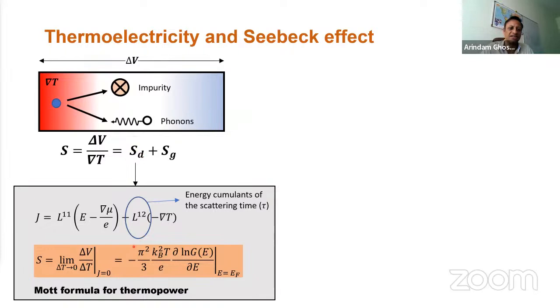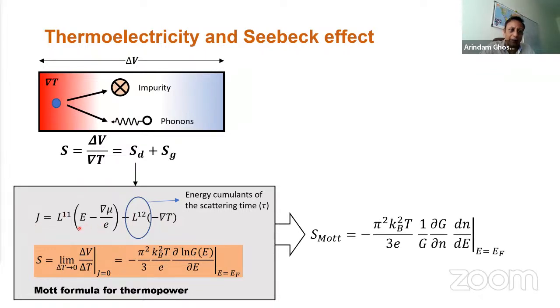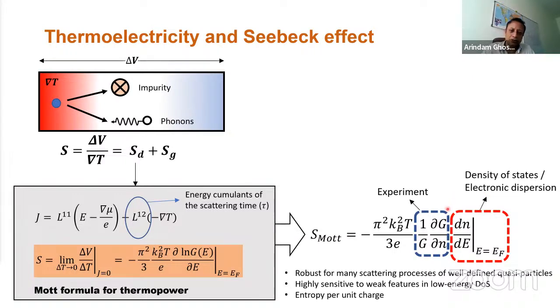One is the diffusion thermopower, which essentially is a conventional Boltzmann distribution, and you have a Mott formula, which is a very robust formula. It comes from the total current being dependent on the electric field that you apply and the temperature difference that you create, and that gives you a thermopower proportional to the derivative of the conductance with respect to energy. Now, this derivative can be split, and one of the advantages of this kind of thermopower is that you can verify this experimentally, because the conductance versus density is what you measure experimentally, and dN/dE is nothing but the density of states. So from here, you can see whether your system is behaving like a conventional diffusive metal, and if there's any deviation from this expression, then you know something interesting is happening.